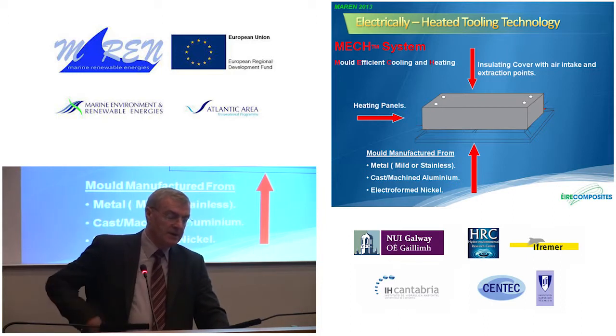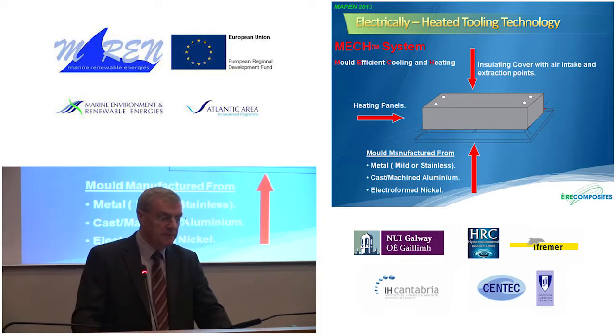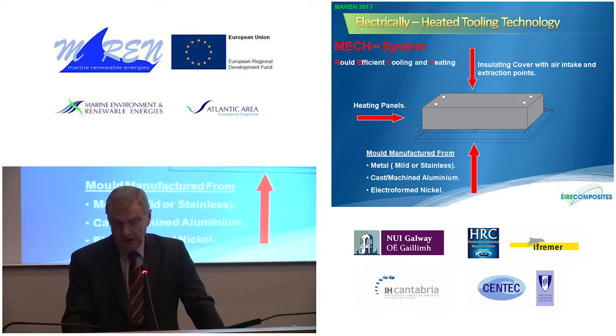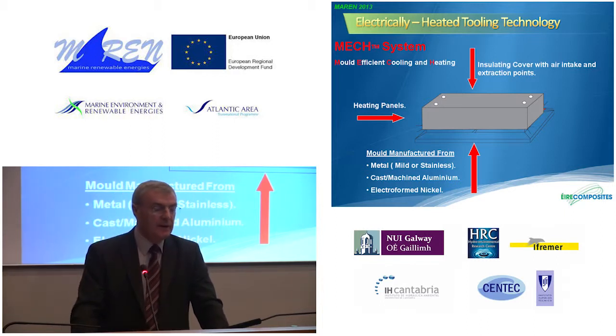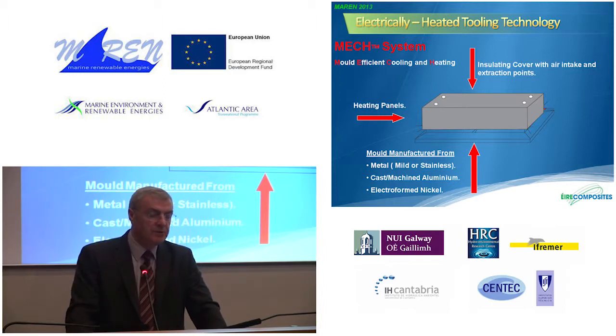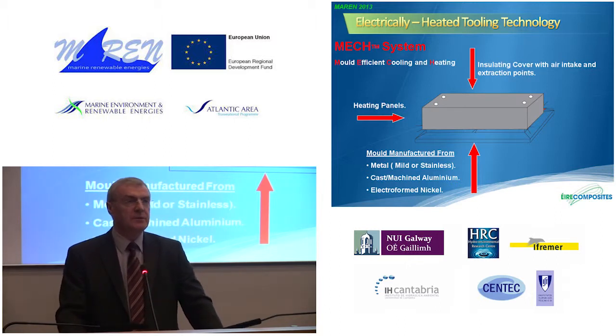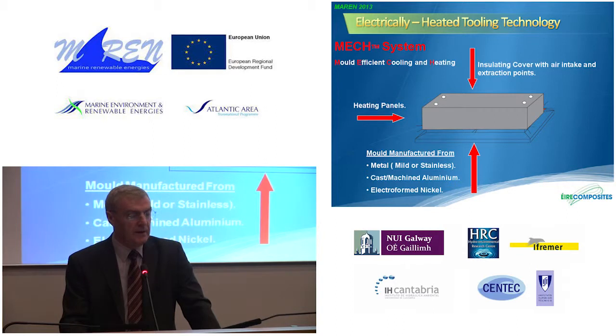equipment. The molds themselves that we worked with were metal, mild and stainless steel, cast aluminium or machined aluminium, or electroformed nickel. And the system worked by applying heating panels on the back or the B side of the mold, and then an insulating cover was placed over it, which was used in the cooling cycle when there was air intake and extraction points, which allowed the mold to be heated or cooled fast.